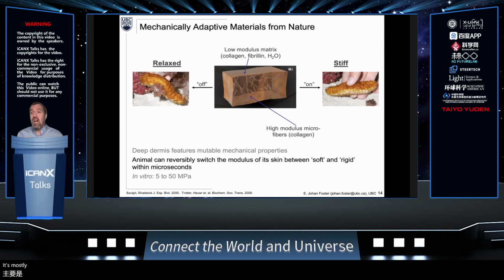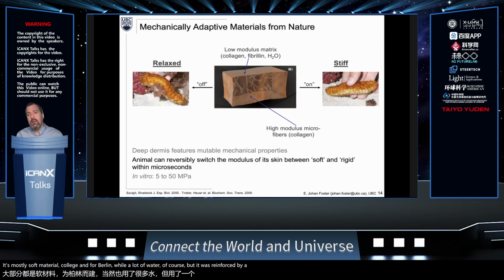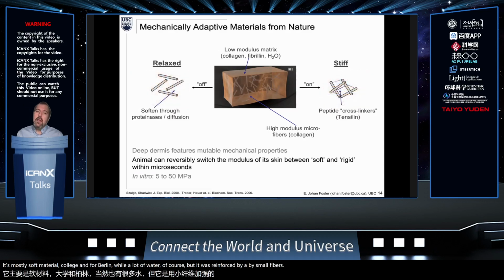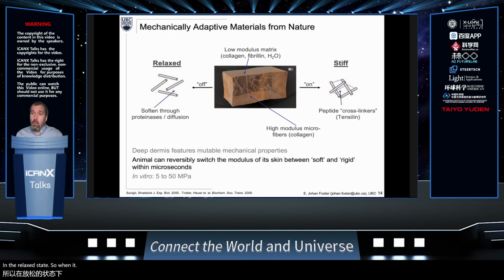It's mostly soft material, collagen, fibrillin, a lot of water, of course, but it was reinforced by small fibers. In the relaxed state, so when it wasn't scared, those fibers are not really interacting. When it is scared, it excretes a protein called tensilin into its skin, which cross-links the fibers within its skin, creates a network of those fibers, and the whole animal becomes stiff. This happens very quickly